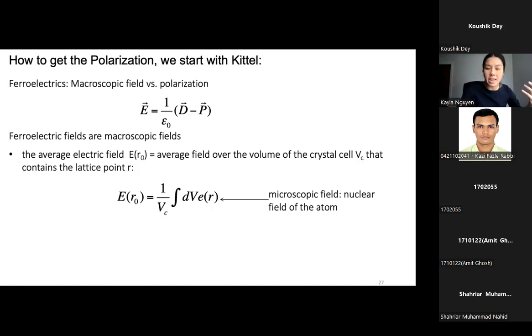Systematically, what this means is that if you have an atomic size probe, for example, an electron probe that is 1 angstrom, that is smaller than the unit cell of your material. And so this is only the microscopic field. So if you're using an angstrom size probe, then you're only looking at this nuclear field. So if you're imaging atoms, you're not actually looking at ferroelectric fields, because ferroelectric fields are macroscopic fields. So what we have to do as scientists, as electron microscopists, instead of looking at individual atoms, is make our probe larger.